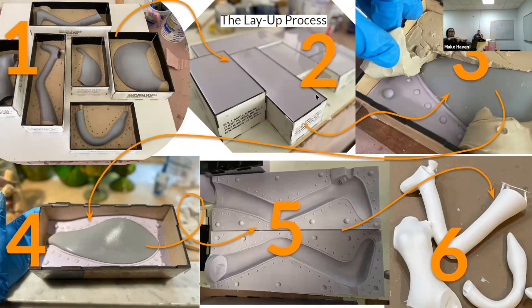Once that sets, you take it apart and flip it upside down, remove the clay blanket, and then you apply a mold release. Here you can see the sort of greasy sheen on there, and pour the second half, and then it'll come apart perfectly at that line. So this is the very, very nice, perfect production molds kind of mold, and it will take much longer than some other types. You get great results.